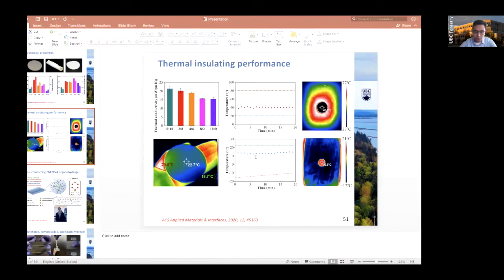Okay, one question. Have you tried other solvents in addition to sodium hydroxide urea during the DIW? This one has not been done. We do work in the lab with some other cellulose solvents, but not for 3D printing. There is some literature where people have done sodium hydroxide with other solvents, but for this work we don't want to completely dissolve the cellulose. Therefore, we choose sodium hydroxide urea because we found that by controlling the time and the conditions, we can partially dissolve the cellulose.